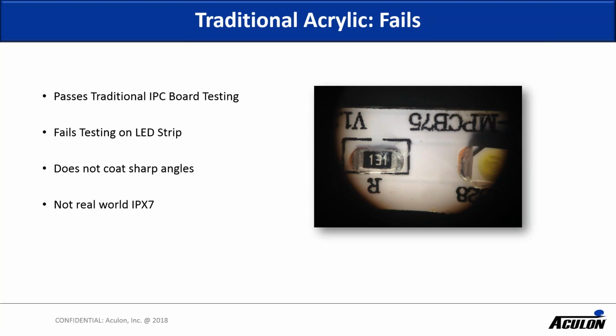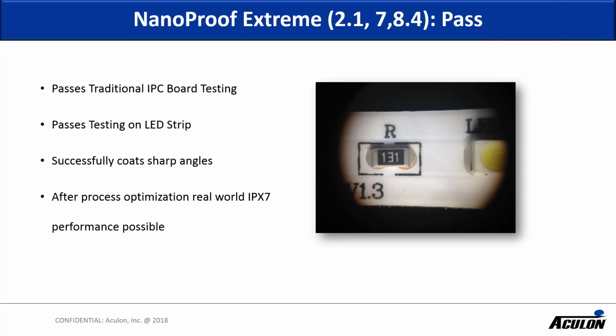Same with the acrylic conformal coating. It passes the IPC board testing with flying colors, but then fails on the LED strip. It does not coat the sharp angles and does not lead to real IPX7 levels of performance. With the materials that we've developed for IPX7 here at Aculon, they not only pass the IPC board testing, but they also pass the LED strip testing, because we formulated them specifically for water protection, and they coat the sharp angles of the components. So after process optimization on your part, real-world IPX7 levels of performance are expected.